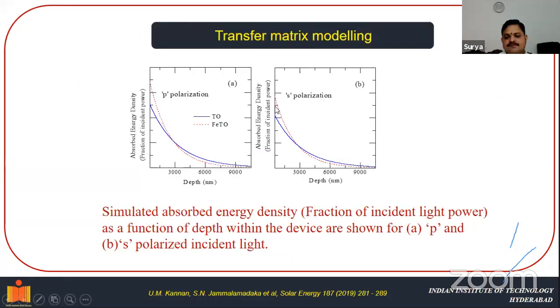So now, on top of the micromagnetic simulations, we also have done the transfer matrix modeling. This transfer matrix modeling gave the information about the absorbed energy density versus depth. As you go deeper into the depth of the solar cell device, how is the energy absorbed for S polarized light or P polarized light? For instance, sunlight will have the S polarization, and it can also have the P polarization.